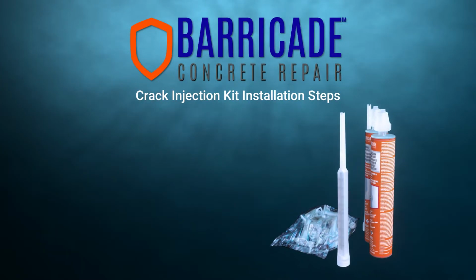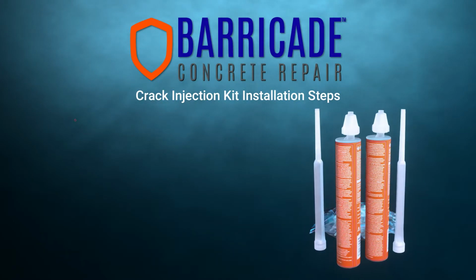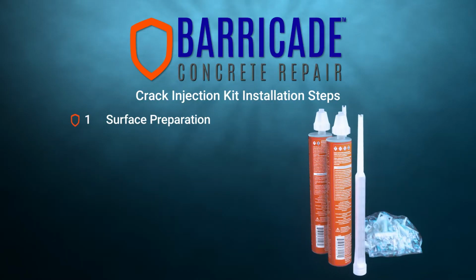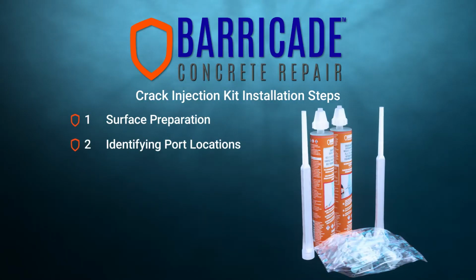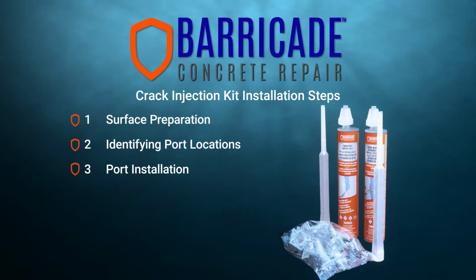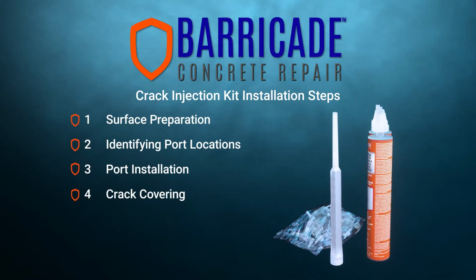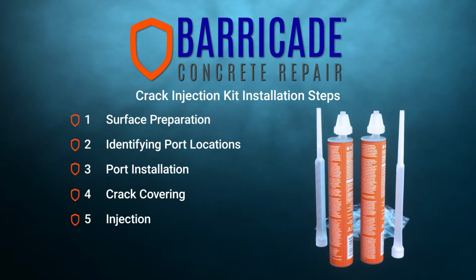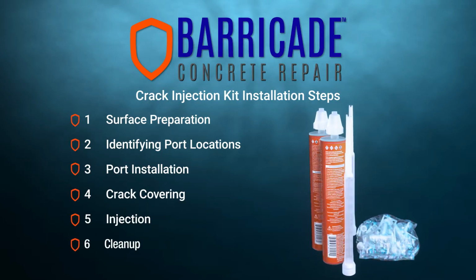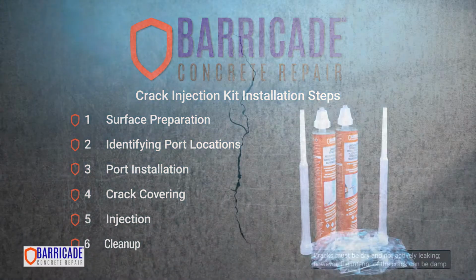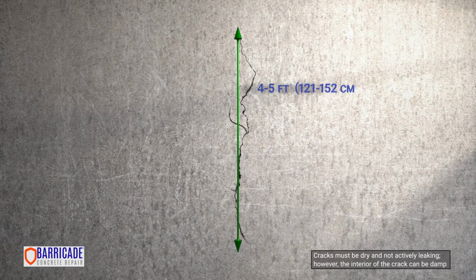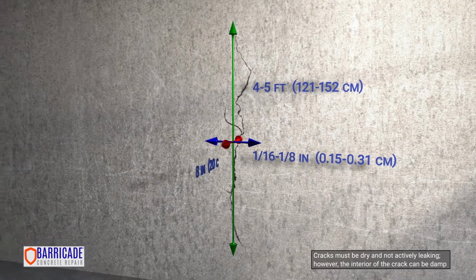The steps required for installing the crack injection kit are: 1. Surface preparation, 2. Identifying port locations, 3. Port installation, 4. Crack covering, 5. Injection, 6. Cleanup. Each kit will fix approximately one wall crack that measures 4 to 5 feet long, 1/16 to 1/8 inches wide, and 8 inches on center.